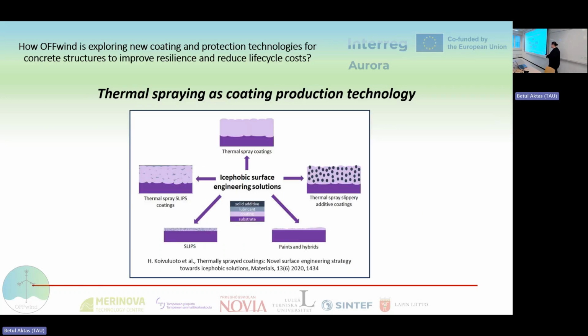But as mentioned, these cold conditions are also bringing new challenges. So these icing conditions are challenging. So these coatings have already shown icephobic properties. So this way we can also get icephobic solutions on the surfaces. And this is just showing that the technology itself can be used on different kinds of purposes and different forms. Or then there are also paints and other hybrid materials, more typical ones that have been used, but then we can go with these thermal spray coatings. So we can get this protection from ice with these coatings, but also other barrier properties, so combining these.